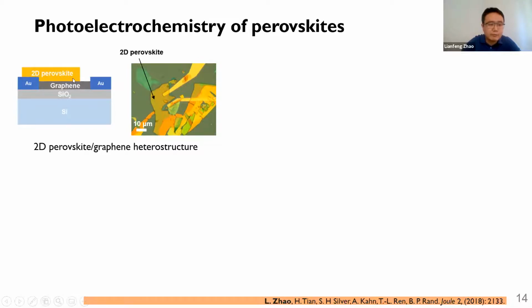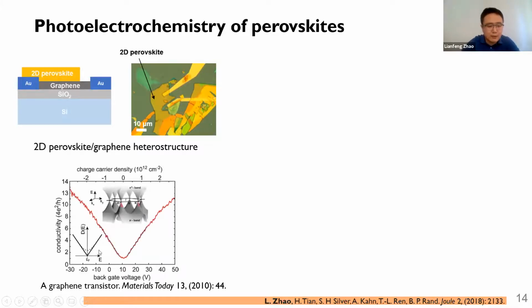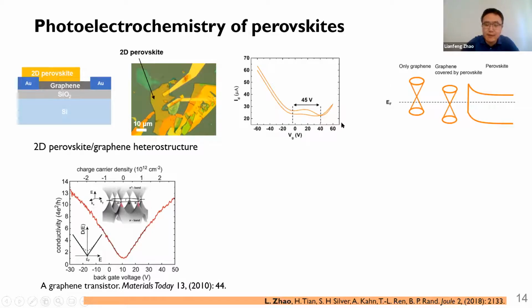We built a 2D perovskite-graphene heterostructure device. And here I'd like to show some background on the graphene transistor. Because of the low carrier density at the Dirac point of graphene, we apply a gate voltage to adjust so that the Fermi level is aligned with the Dirac point of graphene. We will see a current minimum. With this background knowledge, we tested our device and found that there are two current minima.